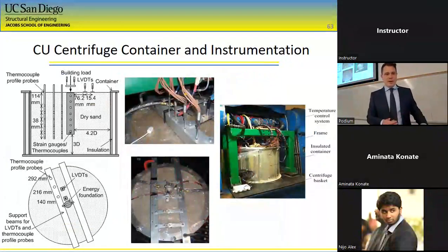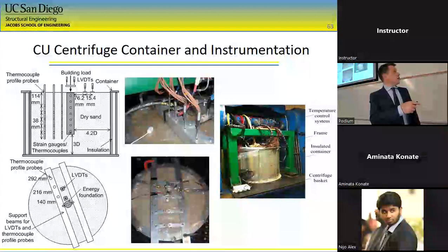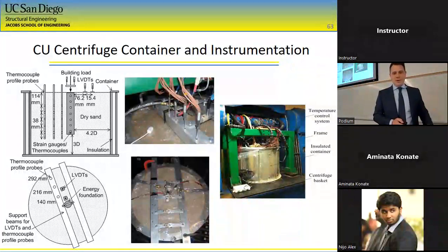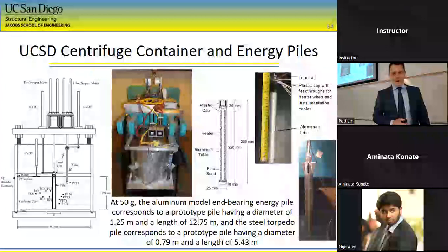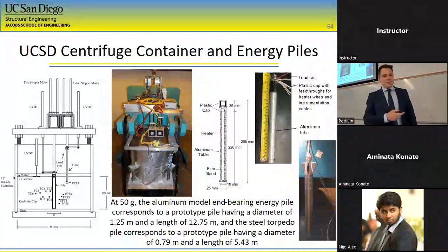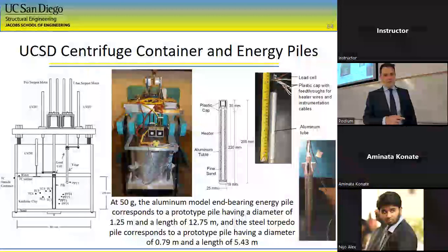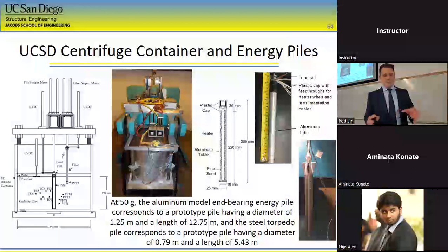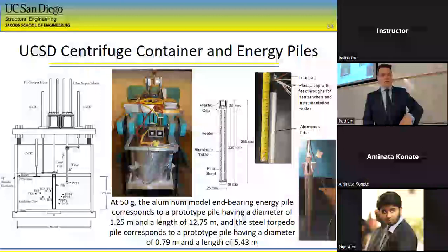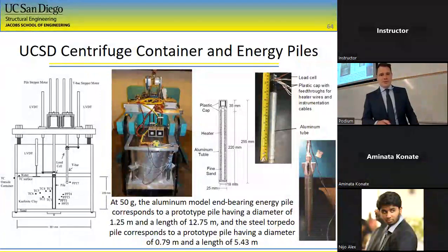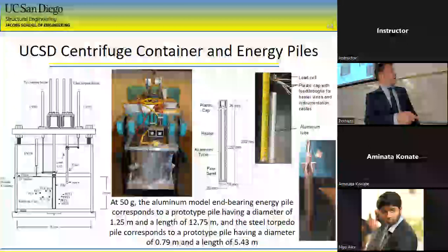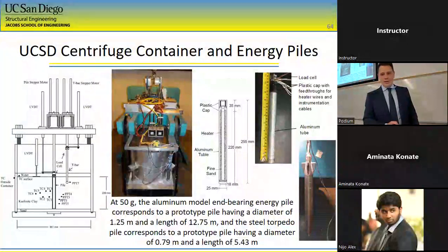And then we put this into a tank in the centrifuge, and we could put a lot of instrumentation to measure the temperature profiles around the pile, measure surface settlement, pile settlement, and applied loads. This is just an example of the centrifuge at San Diego. We were focusing on soft clays there. So we consolidated a clay layer into the centrifuge container. We actually pushed the pile into the clay, heated it, and then pulled it back out. And we looked at both long cylindrical piles as well as heated torpedo piles.